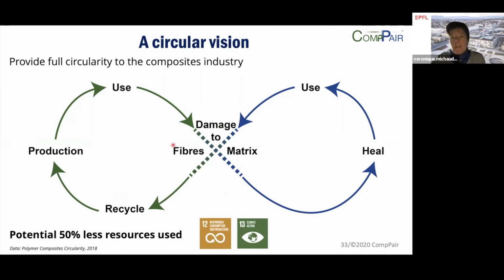Then, if you have a damage to the fibers, of course, we cannot heal this damage. And then, in that case, you need to go to the recycling route, and then maybe production and reuse, or to a normal repair route, which is also possible if the damage to the fibers is only very localized and very minimal. So this really goes in the way of hopefully improving the vision that we have of the composite industry by proposing alternative routes to simply discarding, landfilling, or having to repair even small impacts.